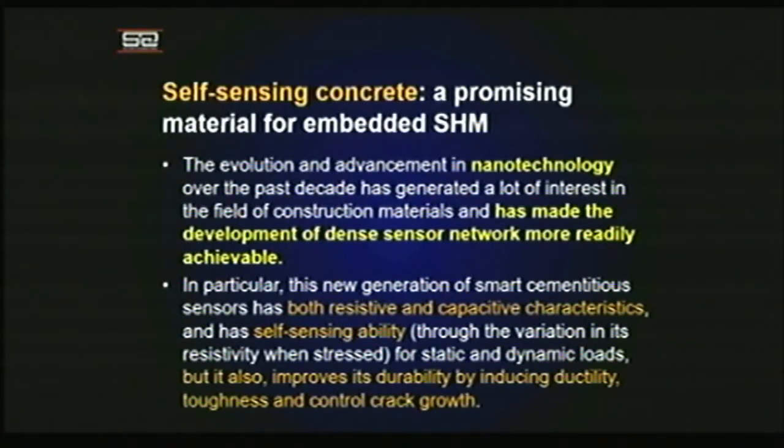In recent days we have moved to nanotechnology-based materials, and one of them is the self-sensing concrete, which is the most promising in embedding SHM systems. This is based on nanotechnology or nanomaterials, which helps in making your structure or the element itself smart, with sensing capabilities. In particular, this smart cementitious material, which can be used as a sensor itself, has both resistive and capacitive characteristics and self-sensing ability for both dynamic as well as static loading.